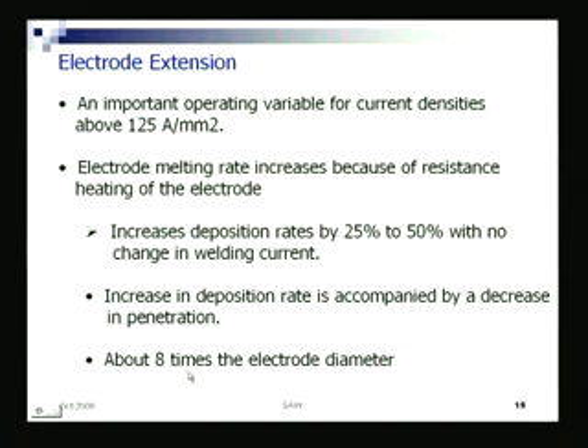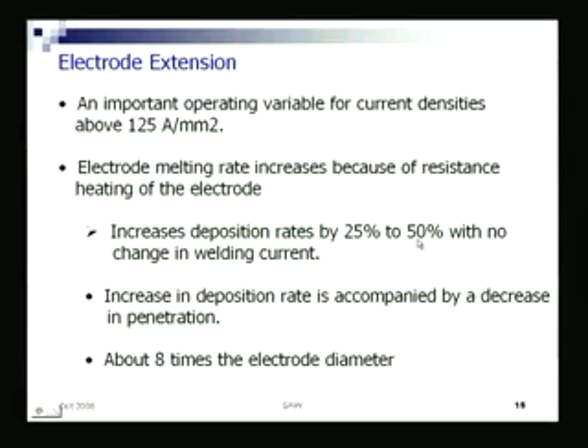Electrode extension for all practical purposes, essentially the thumb rule is 8 times the electrode diameter. Say the electrode you are using is 4 millimeter dia electrode, you generally keep 30 to 35 millimeter long extension. If you go on increasing it, it does not mean the deposition will go from 50% to 80%, because then the electrode length becomes too long and becomes unstable.